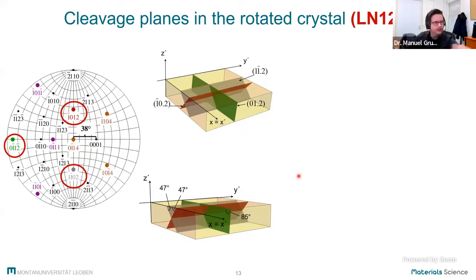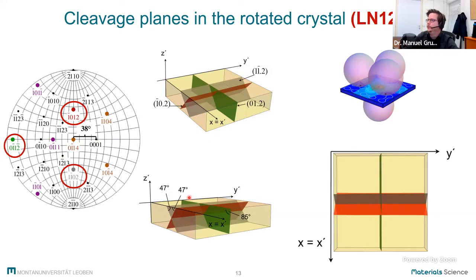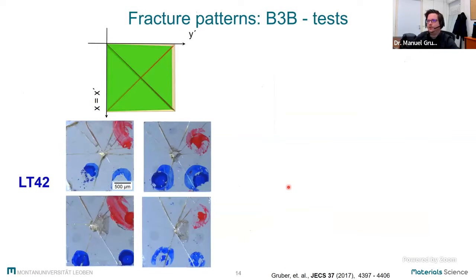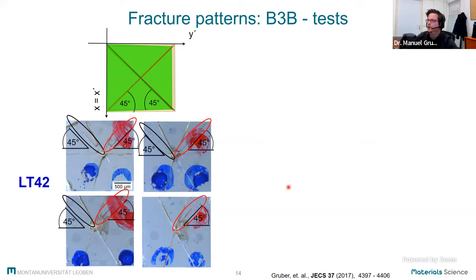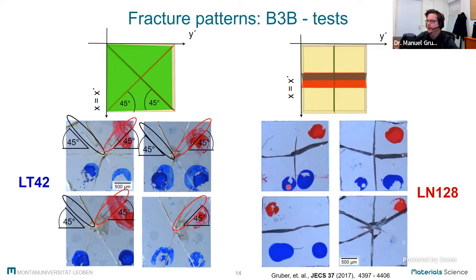to the surface, and the two other planes have an angle of 47 degrees to the surface. If we again compare this with our testing configuration, we would expect fracture, especially along this plane, where we again have the highest tensile forces perpendicular to this plane. Okay, so then we had again a look at our fracture patterns, and we could see that for every single specimen, we could see fracture along this most critical cleavage plane, for lithium tantalate as well as for lithium niobate.